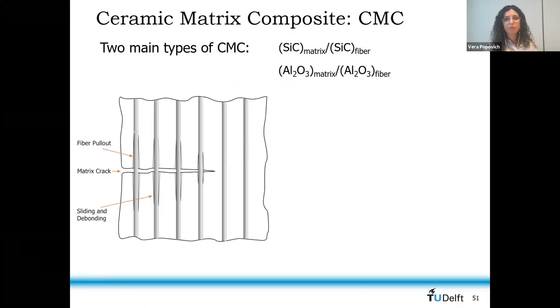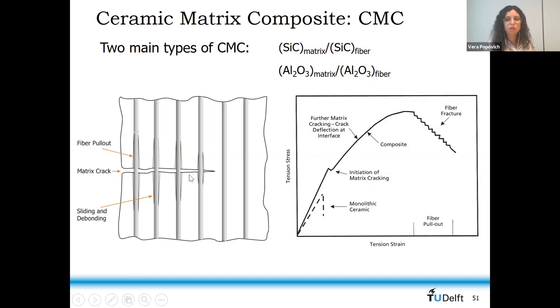So with this, just a few slides, we are behind time. Another example is for sure ceramic matrix composites, and there are two main types: silicon carbide with silicon carbide fibers, or alumina with alumina fibers. They are for sure high strength, but what is important and very tricky with this kind of composite is the interface properties. They have to be not too strong, but not too weak, so that the crack actually goes around the interface along these fibers. So it's not that easy, and for sure the toughness resistance is something that also needs to be considered.